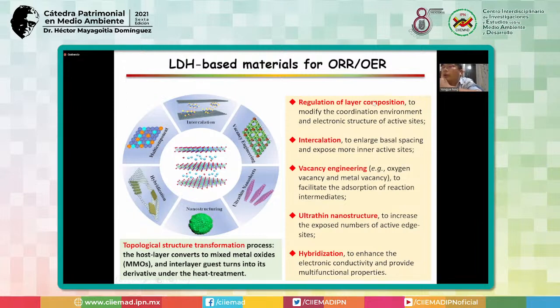By intercalation, we can enlarge the basal spacing and expose more inner active sites. Also, we can build vacancy engineering, the oxygen vacancy and metal vacancy, to facilitate the adsorption of reaction intermediates. Also, we can develop ultrathin nanostructures to increase the exposed number of active edge sites. Also, we can do hybridization to enhance the electric conductivity and provide multifunctional properties.